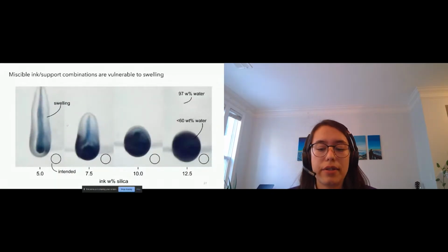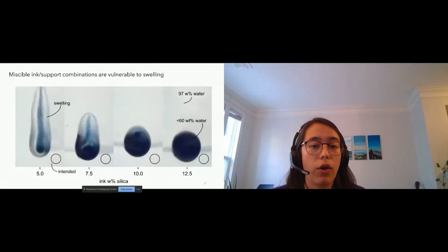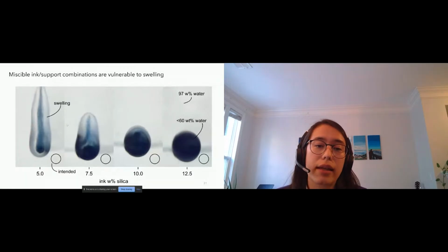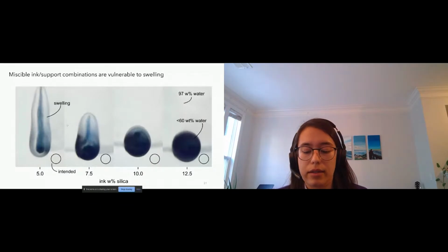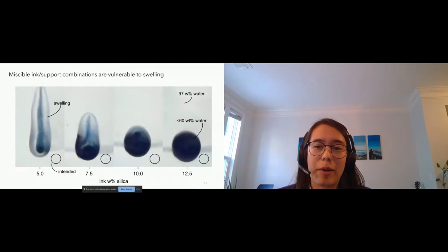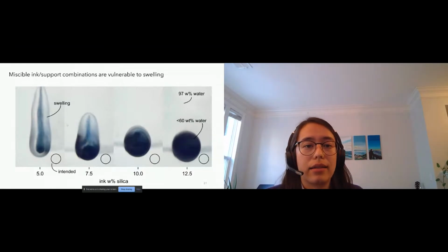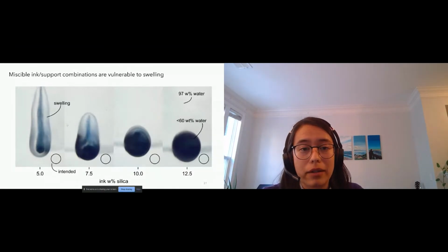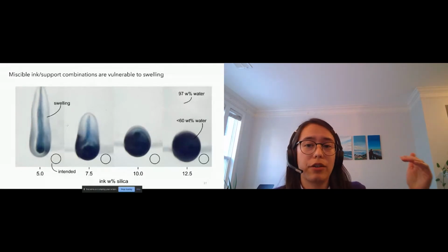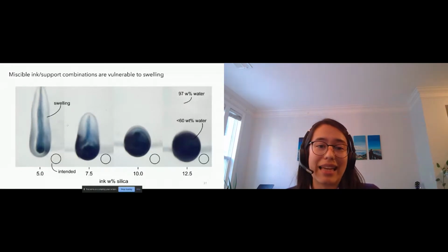Another advantage of using an oil-based ink in a water-based support, or vice versa, is that you can suppress swelling. So these inks are made out of polyethylene glycol diacrylate with water and dye, as well as some fumed silica as our rheological modifier. And you can see here that these filaments are much, much larger than they are intended to be. And the reason why that happens is because these inks are about 60% water, and the support is about 97% water. So you get an osmotic pressure that drives water from the support into the ink and causes